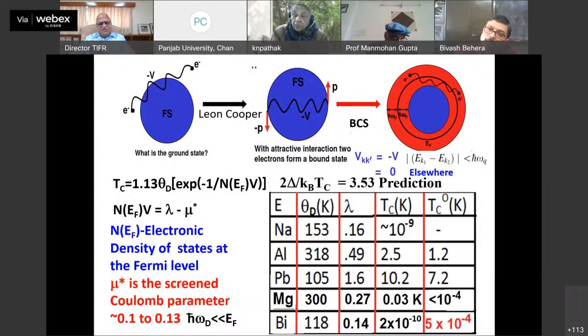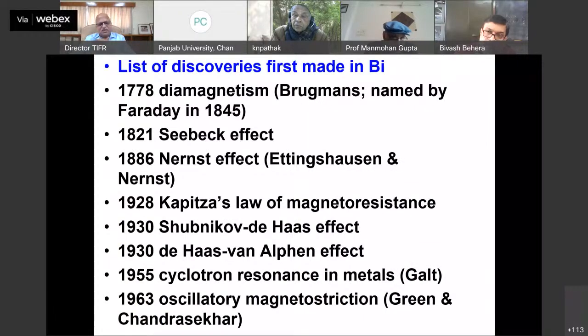But for bismuth, where the lattice energy is comparable to the Fermi level, the theory predicts that it should be at 0.2 nanokelvin, whereas the experiment, as I will show you, happens at something like 500 microkelvin. So, of course, as I said, you should not apply the BCS theory, because the mechanism of superconductivity in bismuth is very, very different from the electron-phonon interaction which I am telling you.